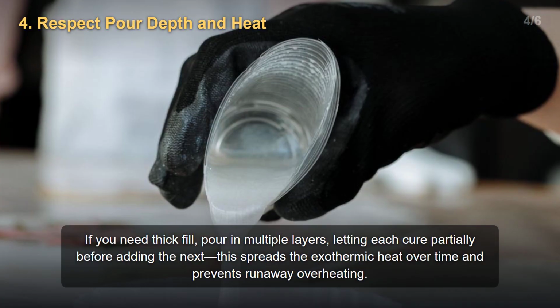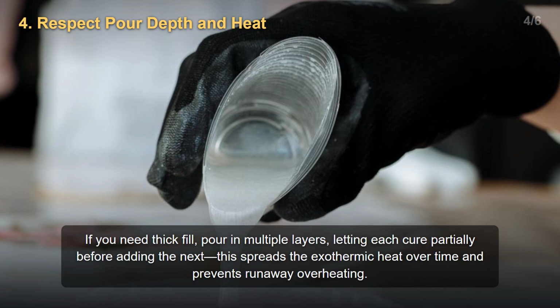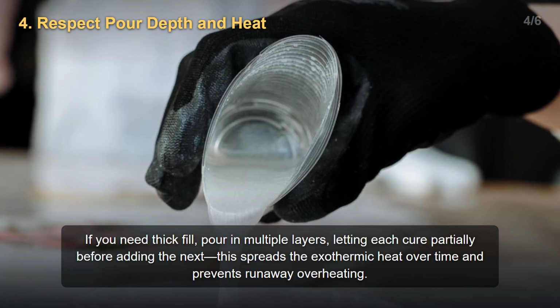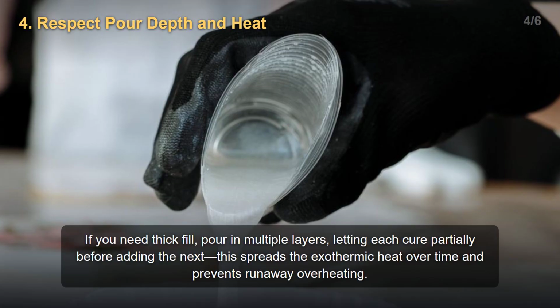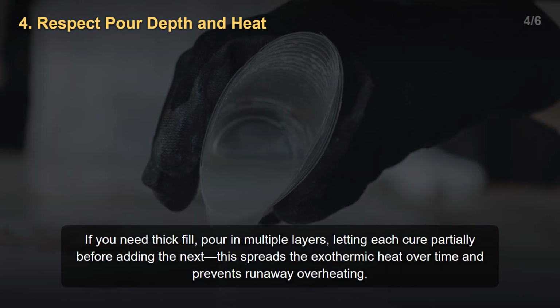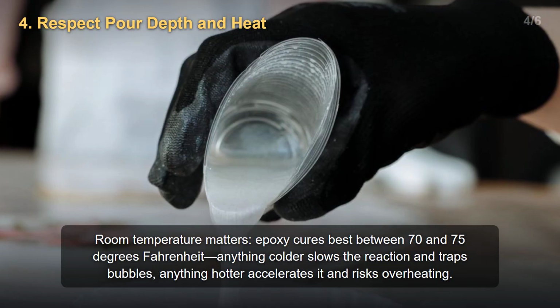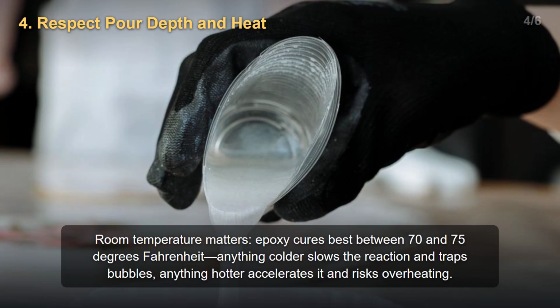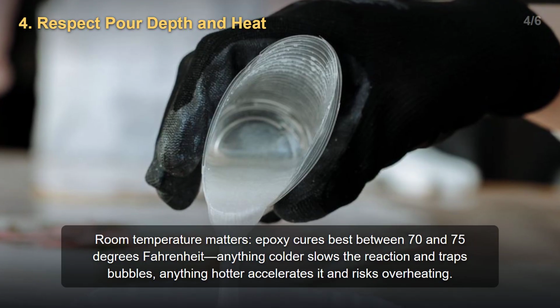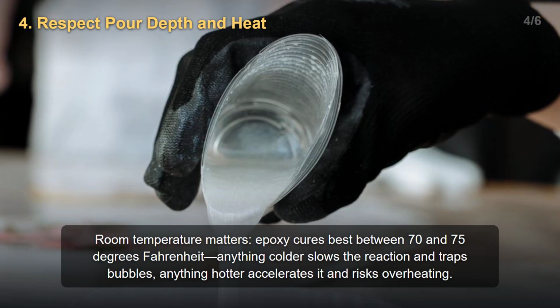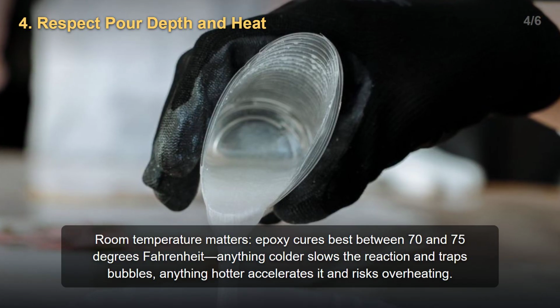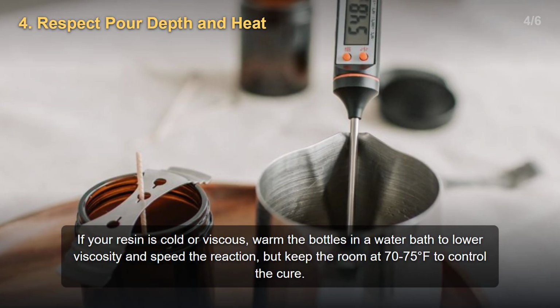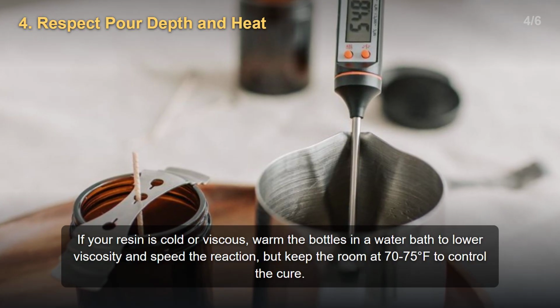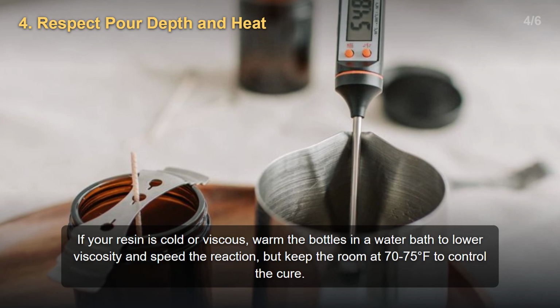If you need thick fill, pour in multiple layers, letting each cure partially before adding the next. This spreads the exothermic heat over time and prevents runaway overheating. Room temperature matters. Epoxy cures best between 70 and 75 degrees Fahrenheit. Anything colder slows the reaction and traps bubbles. Anything hotter accelerates it and risks overheating. If your resin is cold or viscous, warm the bottles in a water bath to lower viscosity and speed the reaction. But keep the room at 70 to 75 degrees F to control the cure.